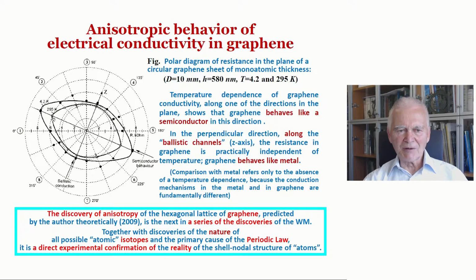The temperature dependence of graphene conductivity found by us during the experiment along one direction in the plane showed that graphene behaves like a semiconductor in this direction, and in the perpendicular direction, along the ballistic channels along the z-axis, the resistance in graphene is practically independent of temperature. Graphene behaves like a metal. So the discovery of anisotropy of the hexagonal lattice of graphene, predicted by the author, is the next in a series of discoveries of the wave model.